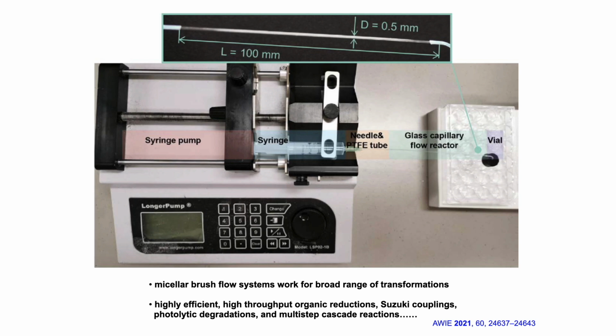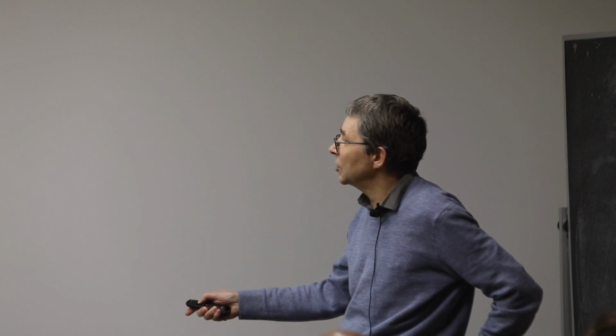I don't have time to go into this in great detail, but you can do all sorts of organic reactions, coupling reactions, photolytic reactions. You can do multi-step cascade reactions where you put a different catalyst in each capillary, and as you flow through your reactant you do a different catalysis at each stage, so you do a multi-step cascade process. This turns out to be a very interesting way of doing catalysis. We published some results on this in 2021, so it's very recent, but it's another area we've been working in.